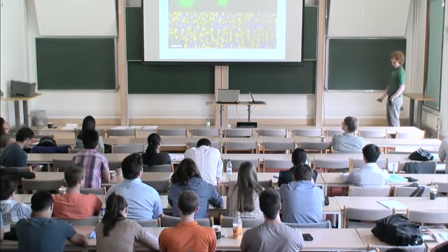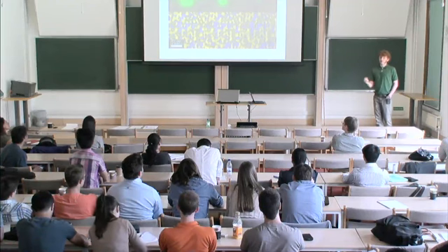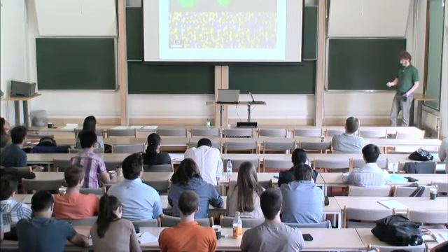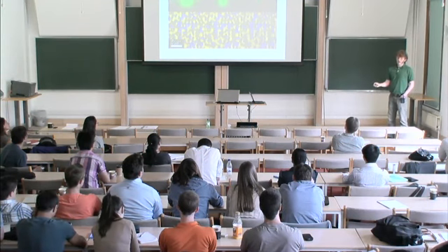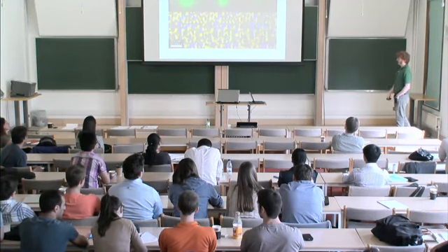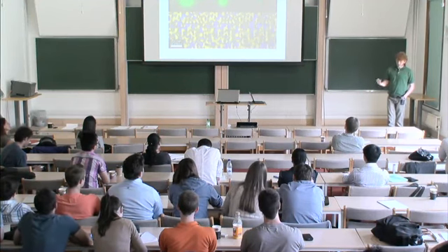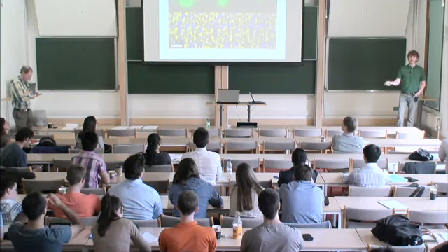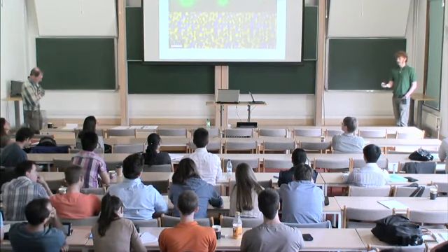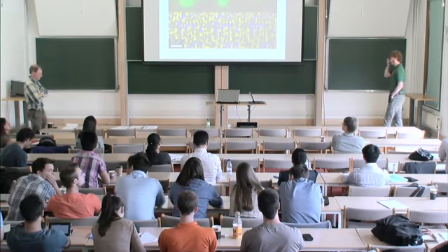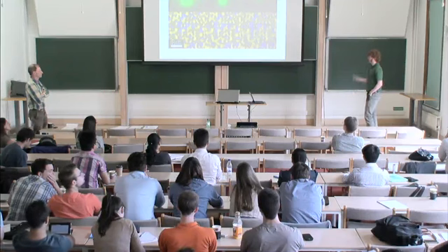Even assuming as simple a system as we can, we get some nice matching with experimental data, and the results are consistent with the statement that there should be some sort of domains of some length scale, and that the shape of those domains changes during stretching of the sample.